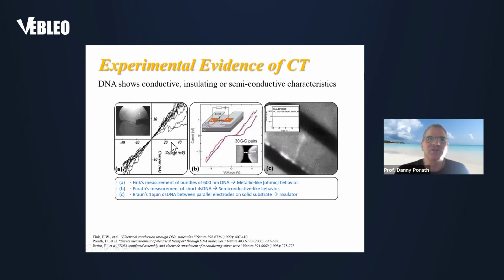Soon after, there was another report by a group in Basel, by Fink and Schönenberger, and they showed that when you take a hundreds of nanometer long DNA molecule between two electrodes, a tip and a metal grid, and apply the voltage, then it seems like an ohmic behavior. This result was not repeated as is. There were probably some problems with the experiment, but these were really two extremes. And this was the background for my decision to join this field.